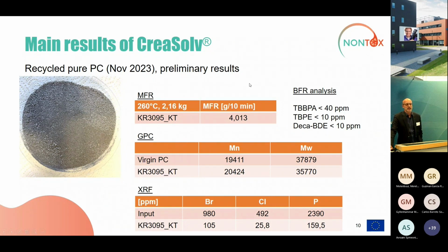Here you see the preliminary results, since the production will be finalized this month. However, we have the analytical data so far, and we indicate the MFR, which is in a good range. We indicate, again, very low BFR analysis, and we see that we do not have any degradation compared to the virgin PC. And again, we also see a clear reduction of bromine and chlorine, and even of the phosphorus, by using this technology. Phosphorus is here an indicator for phosphor-based flame retardants, which sometimes cause some issues in recycling due to related acids production. This is why we considered here to reduce these levels.